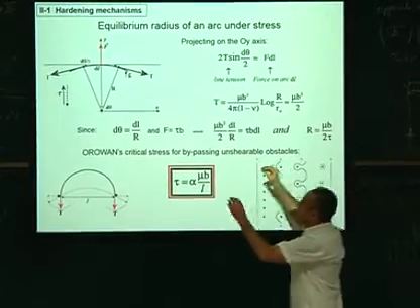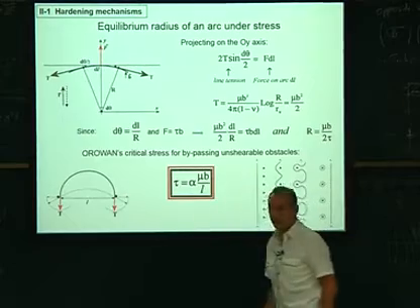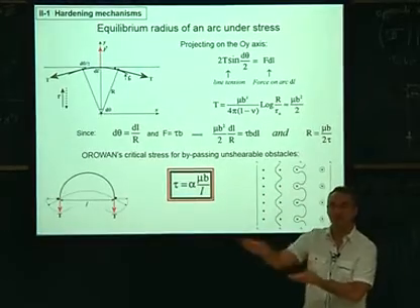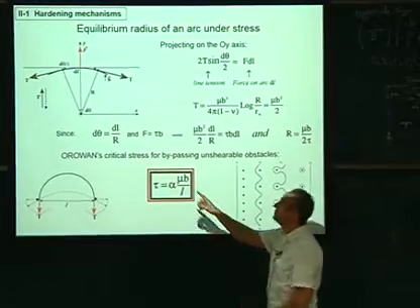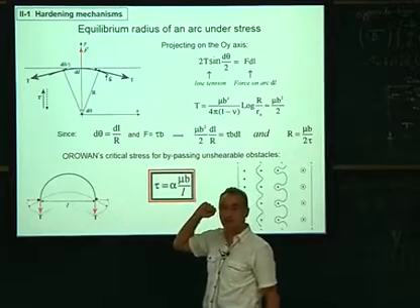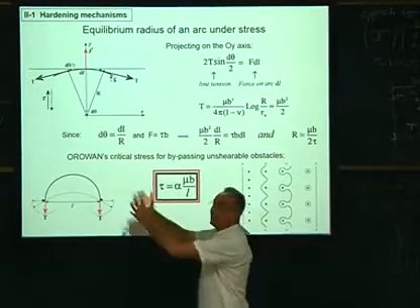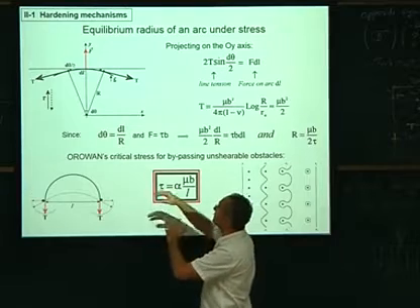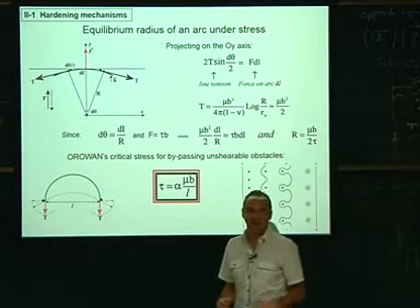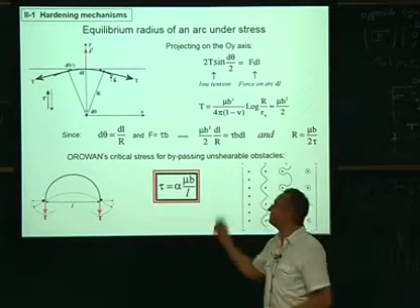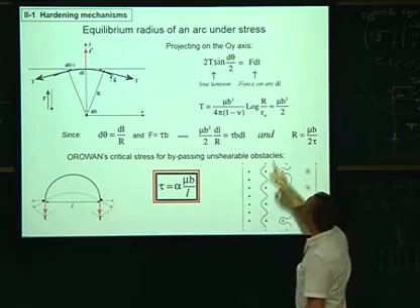And this line tension, which is created on the dislocation, is compensated by the force you apply on it. If you push your dislocation with the red force here, which is called F, then your dislocation wants to bend like this, and you are elongating your dislocation a bit, changing its curvature. Out of that, we can make an equilibrium of this arc of dislocation, which is written here.